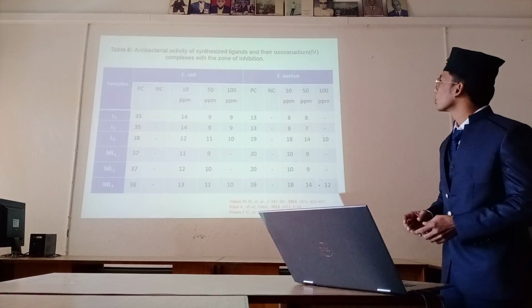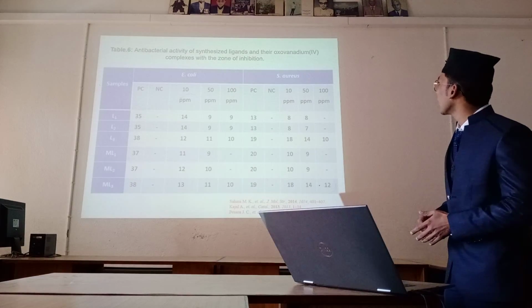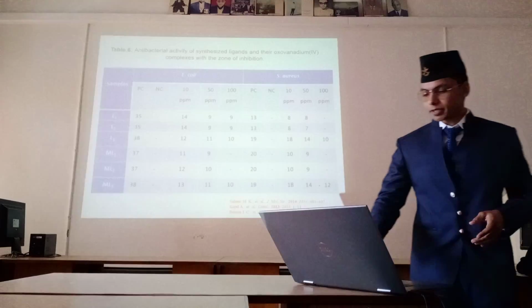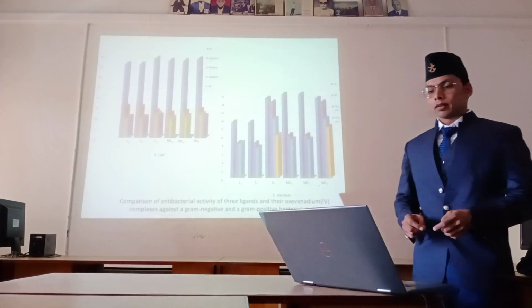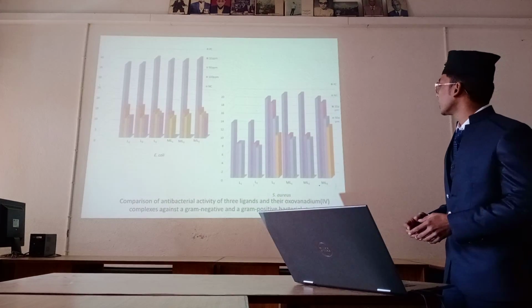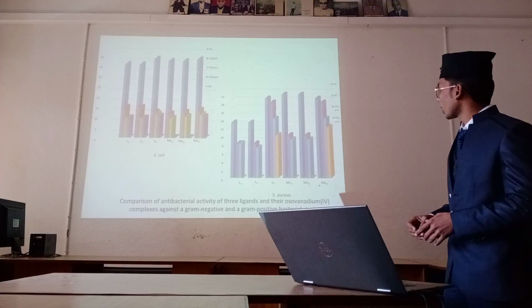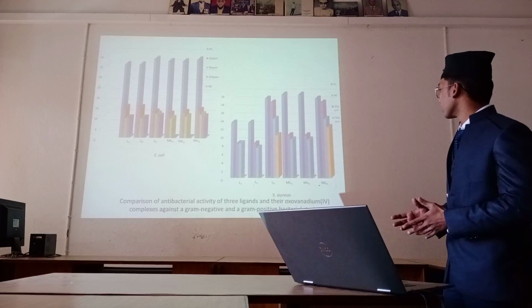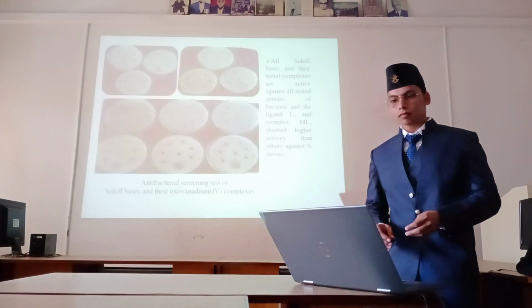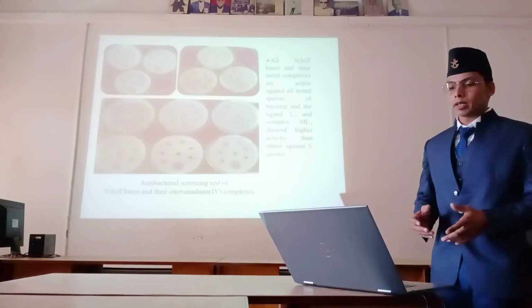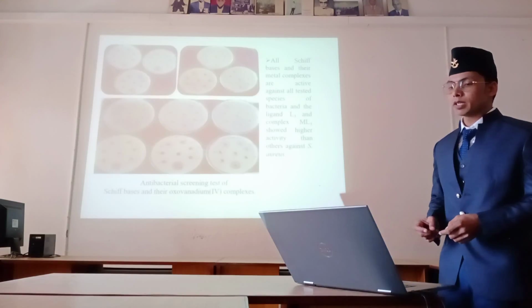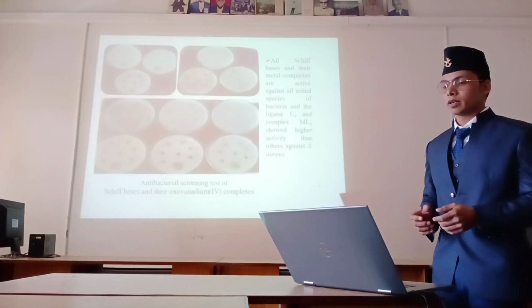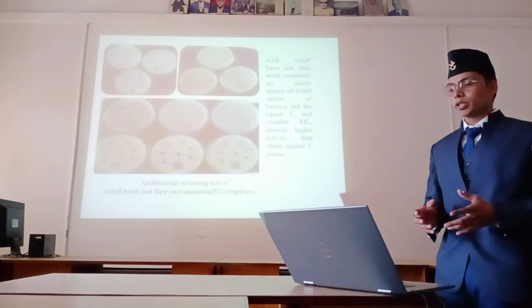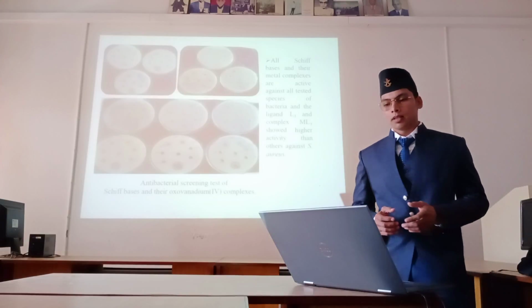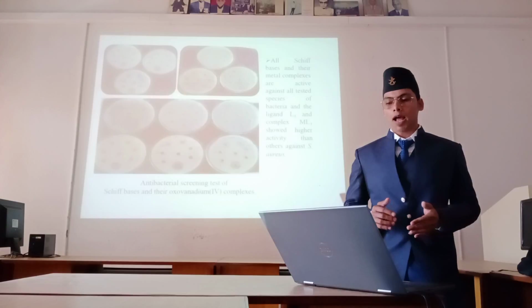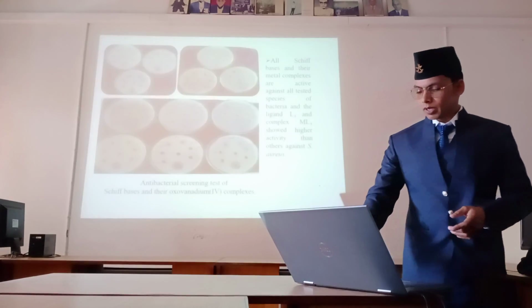And this table 6 shows the antibacterial activity of the synthesized ligands and their oxovanadium(IV) complexes with the zone of inhibition. Here we can see the comparison of the antibacterial activity of the 3 ligands and their oxovanadium(IV) complexes against gram positive and gram negative bacterial strains. Here we can see the antibacterial screening test of the Schiff bases and their oxovanadium complexes. All the Schiff bases and their metal complexes are active against all the tested species of bacteria, and the ligand L3 and the complex ML3 show higher activity than others against Staphylococcus aureus.